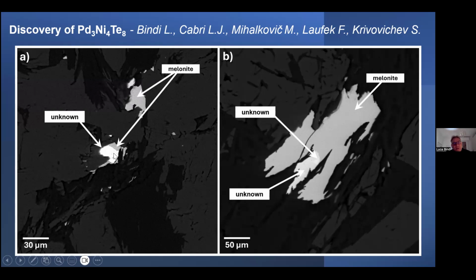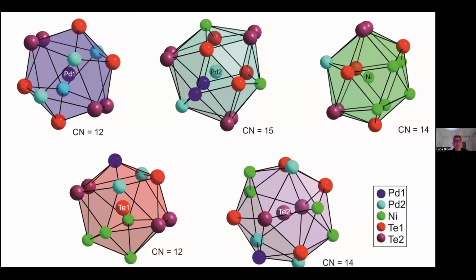What is very interesting is that the bright phase turned out to be interesting from a structural point of view. Actually, it is periodic, so it is not a quasicrystal, but the structure is described as an intermetallic, so nothing strange here, for the telluride of nickel and palladium. What is very strange is, and only if you have good eyes you can see it,